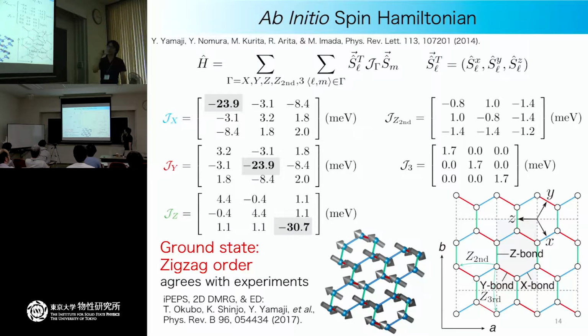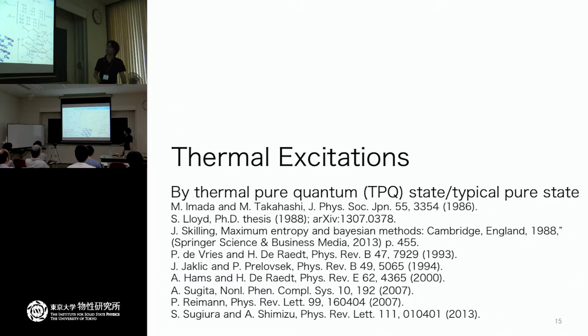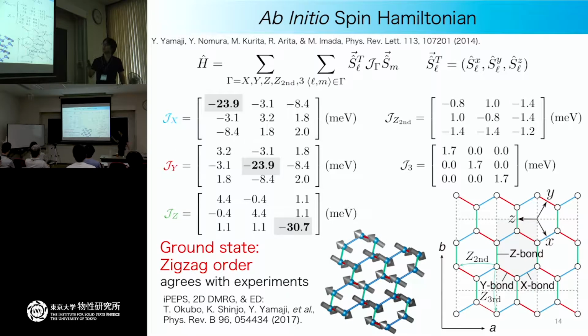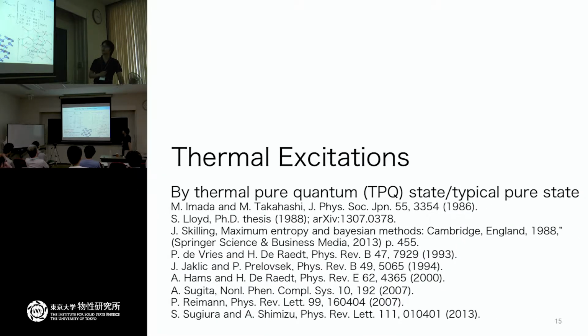However, other detailed couplings give us the zigzag order. First, we examined this situation with exact diagonalization, but later, in our collaboration with Okubo-san, maybe here, and together with Shinjo-san, we found that even with the iPEPS and DMRG methods, we can reproduce the zigzag order found in experiment. This is a really old story, two years ago or something. But starting with this kind of ab initio Hamiltonian, we can tackle the finite temperature signature of the Kitaev model or Kitaev spin liquid, because even if we have a zigzag order as the ground state, still our effective Hamiltonian is dominated by the Kitaev coupling. So maybe if we go beyond the Néel temperature, and look at the high temperature properties of this system, then we can figure out the signature of the spin liquid phase at the ground state.